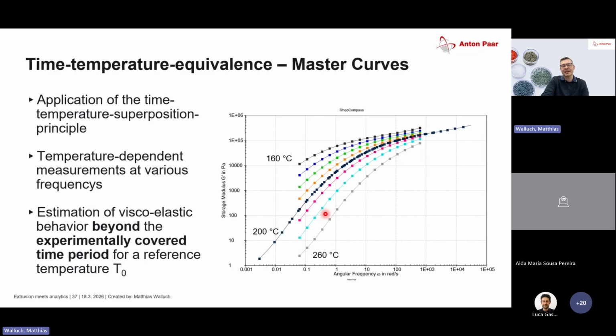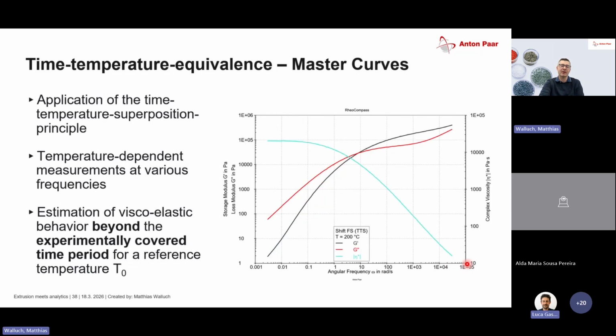Of course it does. This example is also something that you can find in RheoCompass. Here we did exactly the same test between 160 degrees and 260 degrees. It is, I think, a polycarbonate sample, and we just did several frequency sweeps and we shifted them. In this case, you see the storage modulus over a frequency range that starts at approximately 0.01 and goes up to 10 to the power of 5. So we have a lot of decades of material behavior that can be simulated for a certain reference temperature that you want to have. But as you can see here, it doesn't only work for G', it also works for G'' and also for the complex viscosity if you want to know this as well.